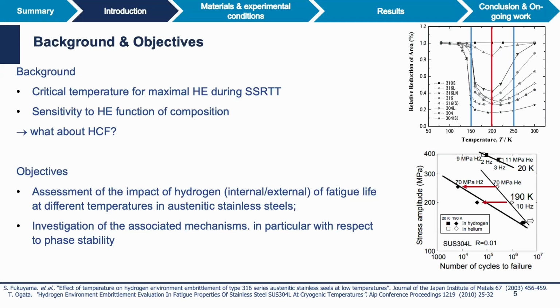So there are only very few data in the literature on this topic. So we can mention the work by Ogata, illustrated here in the case of 304L austenitic alloy. So at this temperature of maximum embrittlement, you can see that we have a loss in fatigue strength at higher stress amplitude values. But if the material is fatigued at 20 K, you have no effect of hydrogen, meaning that the SN curves obtained in liquid hydrogen and helium are superimposed.